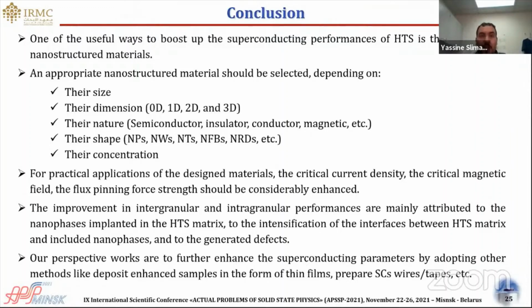So the inclusion of appropriate nanostructural materials could lead to improved intragranular and intergranular properties, which will greatly affect the performances of final products. The implanted nanophases into the high temperature superconductor matrix, and the intensification of the interfaces between the high temperature superconducting matrix and the included nanophases, could play as efficient pinning centers to minimize the motion of vortices.